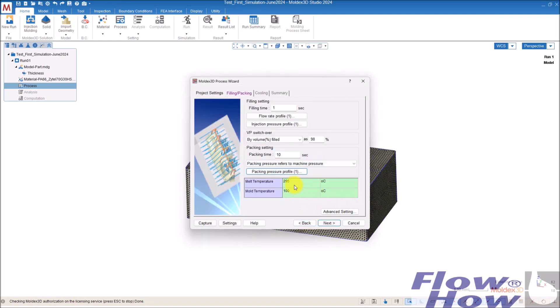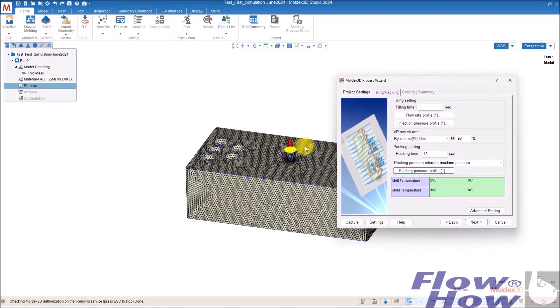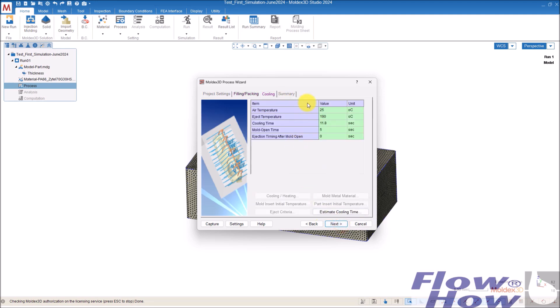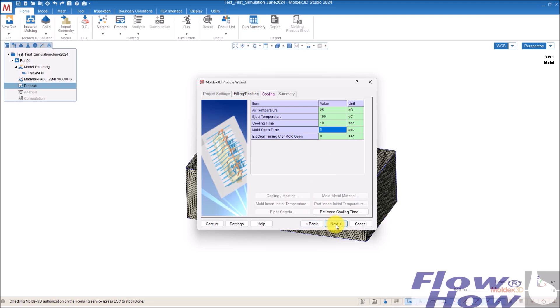Melt temperature. That is the temperature on this face. Mold temperature, that's the uniform temperature of the mold, and it's related to this temperature. So I can't, if I don't have cooling channels, I can't get hot spots in my mold. It's just a uniform mold temperature. The next one is cooling. As I don't have any cooling, it doesn't matter. But this cooling time can have a small effect on the packing calculation, because it calculates the shrinkage until end of cool. So I'll just put in ten seconds. It doesn't matter so much in this case.